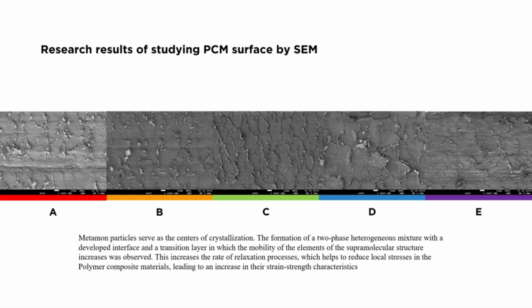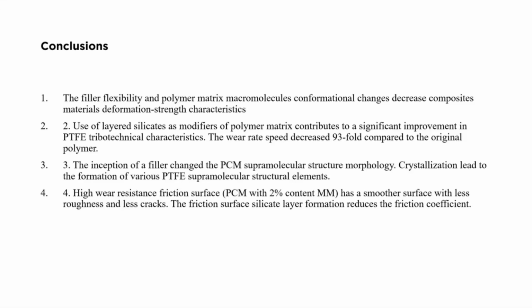The formation of a two-phase heterogeneous mixture with a developed interface and a transition layer, in which the mobility of the elements of the supramolecular structure increases, was observed. This increases the rate of the relaxation process, which helps to reduce local stresses in the polymer, leading to an increase in strength characteristics. In conclusion, we can say that the filler flexibility and polymer matrix macromolecular conformational changes decrease polymer composite materials deformation strength characteristics.